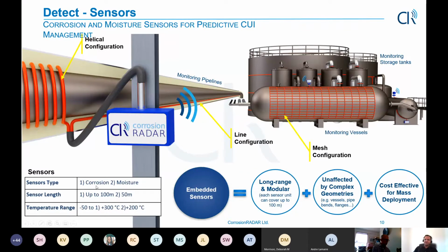So as far as the principle is concerned, the corrosion sensor is a multi-layered structure of wire, and the outermost layer is sacrificial. So sometimes I call this the longest coupon in the world, where you put a carbon steel layer inside an insulation, and wherever water is coming in, it starts to corrode. And then the second problem, when you have the longest coupon in the world, is where that coupon is getting corroded, and we use the electromagnetic radar principle for that. So we send microwaves inside and using time of flight locate exactly where it is.